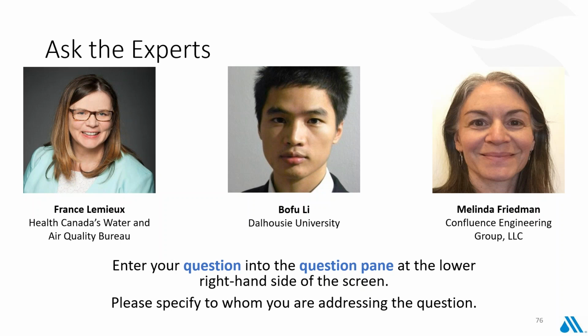As I know, not too many water utilities are using sodium silicate for corrosion control, but when I read some documents, I found many Canadian water utilities are using sodium silicate for sequestration. So my suggestion is that when we use sodium silicate, no matter for corrosion control or sequestration, we need to carefully evaluate the dosage. Because, for example, if we find some problems with the pH in the system, sometimes a water utility will increase the dosage, but overdosage may result in increased dispersion of the scale. So I think carefully evaluating the dosage and trying to understand the mechanism is quite important for the industry.